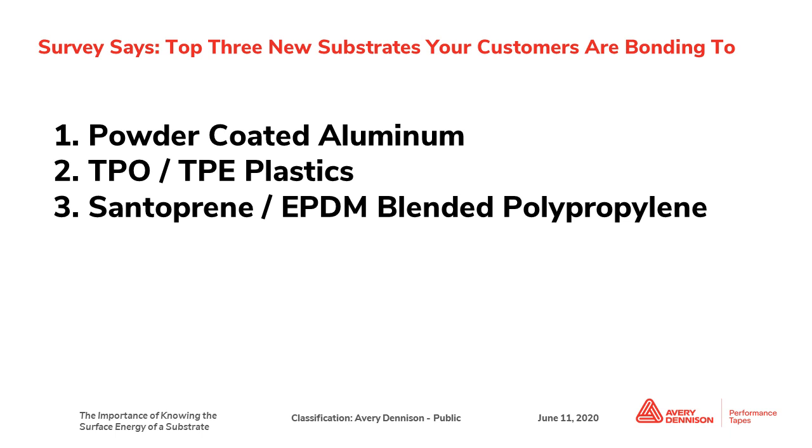So in that situation, because they're low surface energy and they have plasticizer, we would recommend something like our general purpose acrylic, which is a modified acrylic that can bond to low surface energy materials, but then also resist the plasticizers that might creep in there. A rubber adhesive would bond well to a flexible TPO at first, but you might notice after a week or so that the part may have fallen off and that the adhesive basically turns to a really weak, fragile goo. That plasticizer can vary quite a bit, so we have to be mindful of that type of thing.